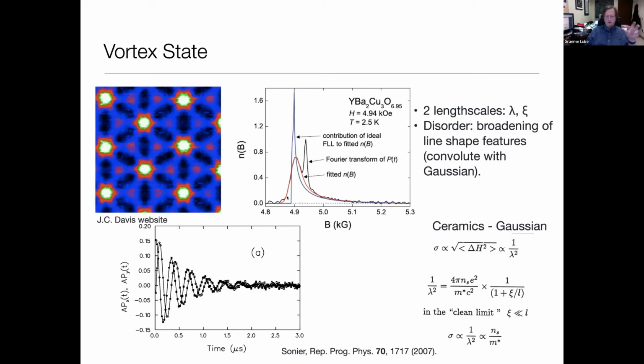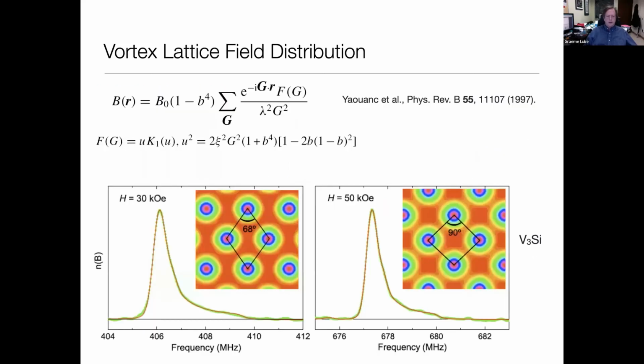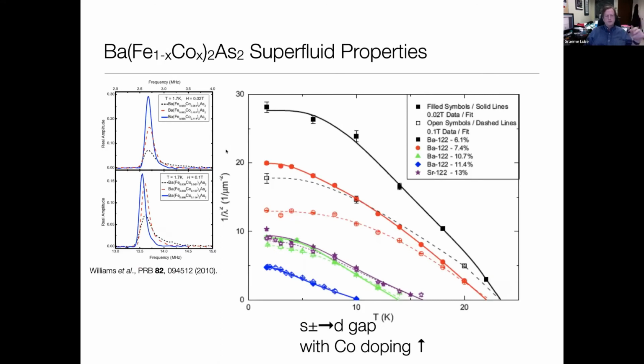If the vortex lattice is a bit disordered, then maybe you can't do that in quite as much detail. But the overall line width, which is the width of the field distribution, is essentially given by the magnetic field penetration depth, which depends on essentially the superfluid density divided by the effective mass. So in a superconductor, if you can measure the broadening of this precession signal, you directly measure the superfluid density, ns over m star, and then you can measure its temperature and field dependence. Here's something in more detail: you can determine things like the vortex lattice geometry. If you have a well-defined lattice, you can really see all of these details and measure directly the coherence length and the penetration depth, etc., and determine the geometry. We've done this, for example, looking at iron arsenic superconductors. We can see as you change some of the doping, we're looking at the temperature dependence of the superfluid density here, which is 1 over the penetration depth squared.